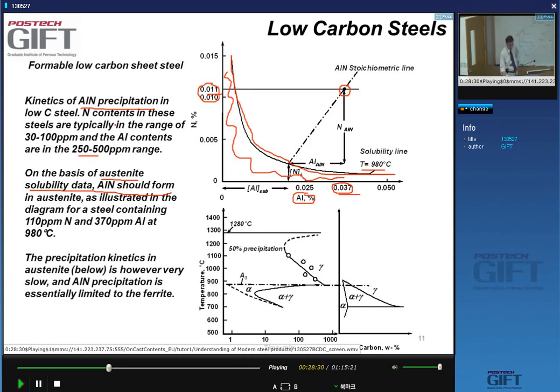And you can see this here. This is the precipitation temperature time diagram for aluminum nitride. This is the precipitation curve for aluminum nitride in austenite, and you can see that it takes a very, very long time for us to start noticing the precipitation. This is a log scale again, so 50 is about here somewhere. So it takes like 50 minutes for aluminum nitride to precipitate. 50 minutes, that's an hour. By the time an hour has passed, the slab has long been processed. So it doesn't precipitate.